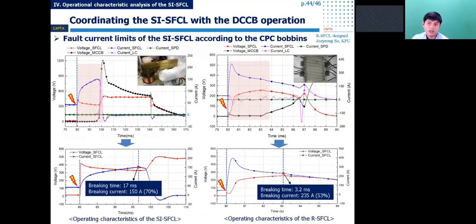The operating characteristics of the SFCL were tested and compared with a resistive SFCL module. In case of using the resistive SFCL, it needs time to increase the resistance during the quench. So there was a very large source current here from the starting. Therefore, the circuit breaker can detect the fault and break much faster. It's very fast. However, the large source current like that is very dangerous for the power system.